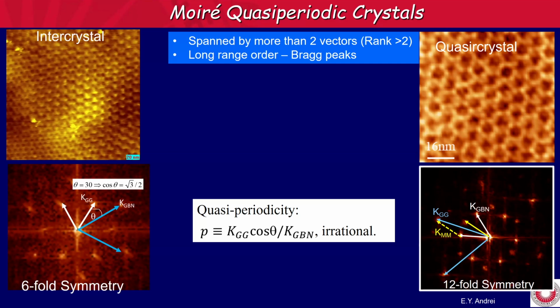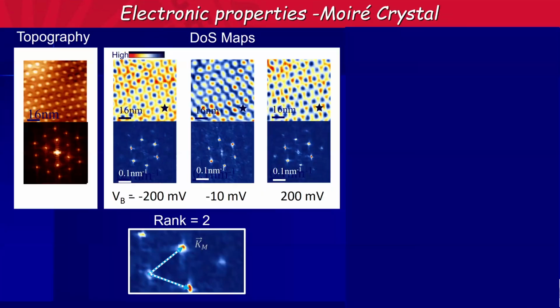It is not a perfect quasi-crystal. It's a little bit distorted, but that's as good as we can get it. Just to summarize here, what we want to look at is the electronic properties. Here we have the perfectly aligned crystal, and we see that no matter what the energy is, when you look at the density of states map, you have the six-fold symmetry. Okay, so this is the Moiré K vector.